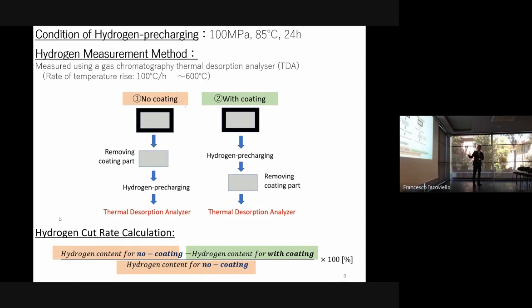Second, coated specimen, hydrogen precharging, and remove the coating part, TDA. So if I compare these materials, we can know the coating effect against hydrogen ingress. So I calculate the hydrogen cut ratio by this formula.